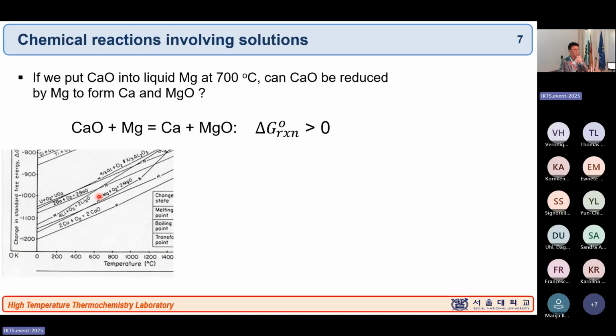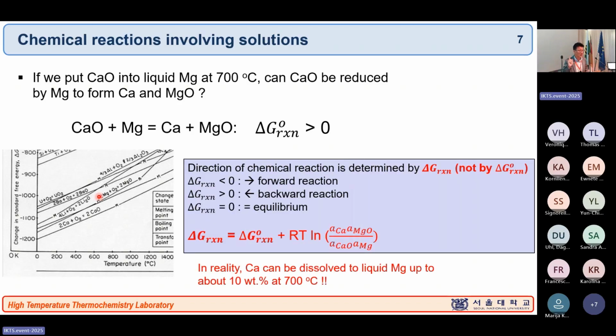So when you ask what the equilibrium condition is, you are not only looking at the delta G naught of reaction. You have to look at really delta G of reaction. This is a very important lesson for you. When you're talking about the reaction direction, the delta G of reaction value is important. And delta G of reaction equals delta G naught of reaction plus RT ln of all the activities and partial pressures we learned. I'm going to introduce activity a little bit later. So this is the equation we have to look at. And if the component, reactant or product, is in pure standard state, the activity equals 1.